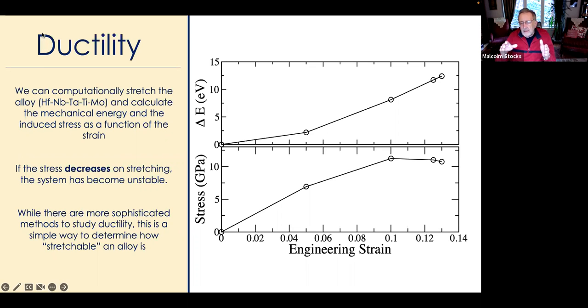And what you can do then is ask, at lower temperatures, does the energetics allow you to have more than one phase? We developed a whole theory along those lines, and it turned out to be very useful. We have the CPA as the description of the ideally infinite-temperature disordered phase, and then you can look for the instabilities in that. That's basically what the approach we developed does, and it works quite well.